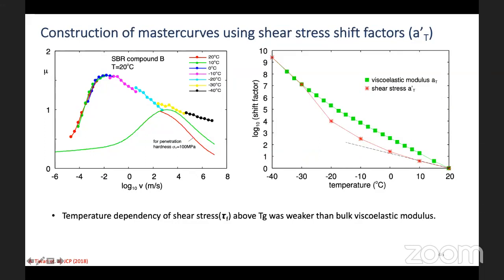And then we realized that the adhesive contribution to rubber friction has a different temperature dependency, in the sense that, if you see on the right, this green curve shows the shift factors that we get by using bulk viscoelastic shift factors. And this red curve is what we obtained when we formed a smooth master curve. Then we realized that the adhesive contribution to friction has a different temperature dependency than the bulk.